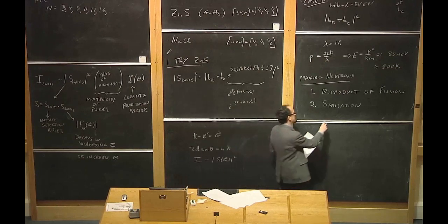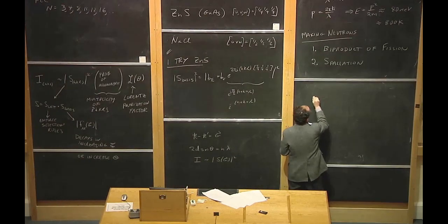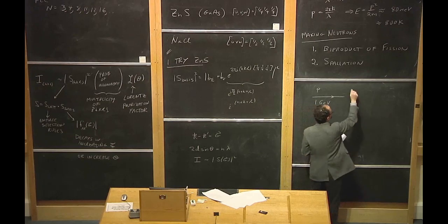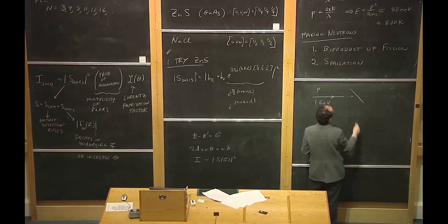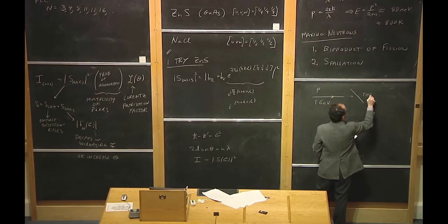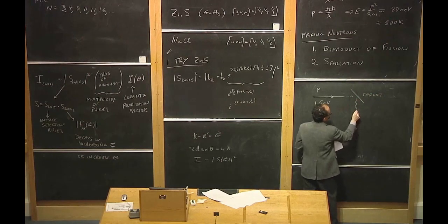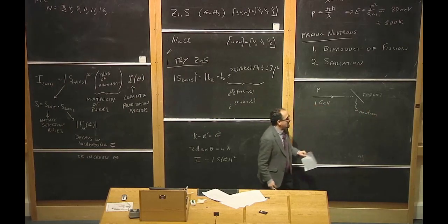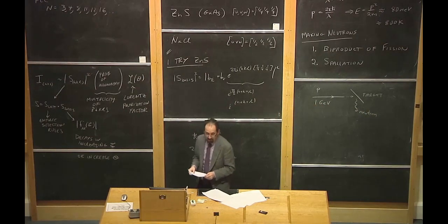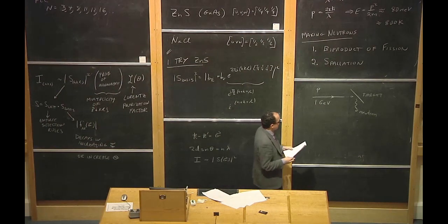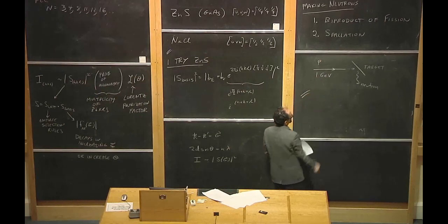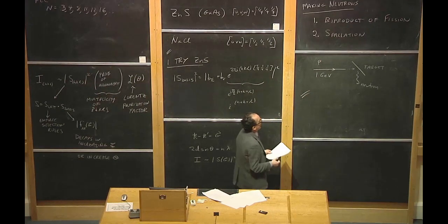The idea of a spallation source is not unlike the idea of an X-ray tube, where you take usually a proton, and you accelerate it to about a gigaelectron volt, and you hit it onto a target, and the idea is to smash some nuclei and kick off some neutrons. Now again, since you're hitting it with such a high energy, you're going to kick off neutrons with some very, very high energy as well.